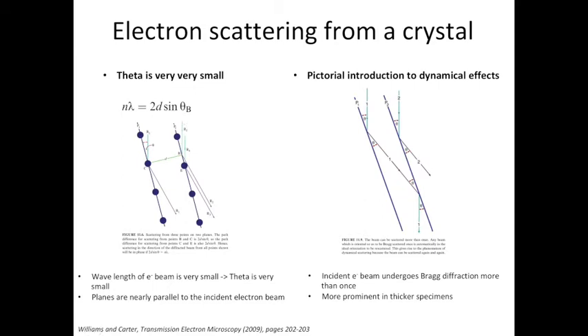The second thing I'd like to briefly mention is something we call dynamical effects. When the electron beam undergoes Bragg's diffraction, it does not have to only diffract once. In fact, if we look at the first beam here, it can get diffracted multiple times by the same set of planes. If you follow beam number one, you can see it's getting diffracted once, then twice by the same set of planes. This is called dynamical effects. In most of the analyses we'll carry out in the next few weeks, we will not worry about this. We will mainly focus on the kinematic effects of diffraction. But you need to bear in mind that dynamical effects can also occur. Dynamical effects become more and more prominent when we deal with thicker specimens.